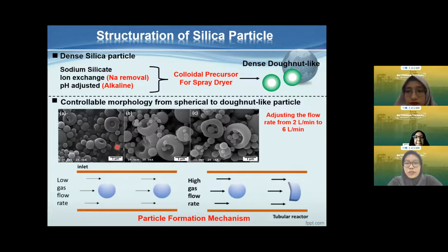And then how about if we adjust the flow rate of the carrier gas? Here we can get donut-like particles, but the diameter of the donut particle is so big if we increase the flow rate. So here I give the particle formation mechanism if we increase the flow rate of the carrier gas.